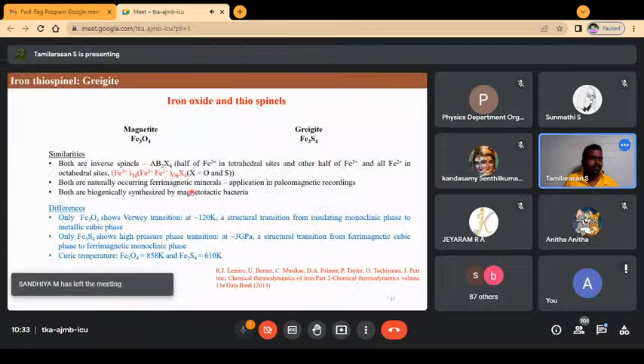So let me give a brief introduction on the material. We were interested in studying the surface energetics to begin with. So it's an iron thiospinel, Fe3S4, and it's a mineral named greigite. It's structurally analogous to magnetite, which is the oxide spinel of iron. It's an inverse spinel having half of the 3 plus in tetrahedral sites and the other half in octahedral sites along with 2 plus, unlike normal spinel where you would find everything ordered.